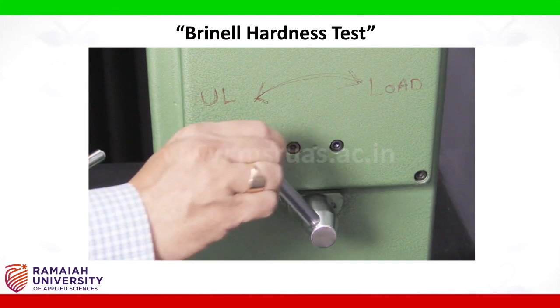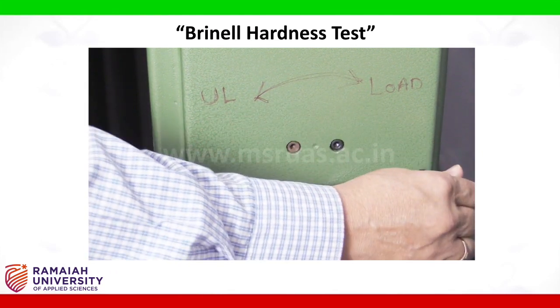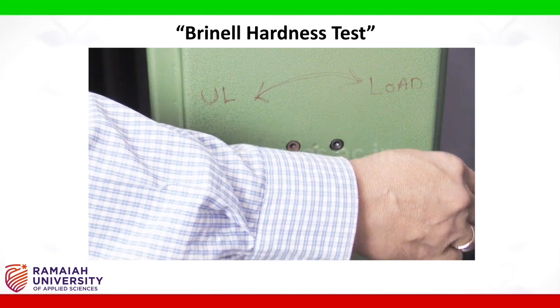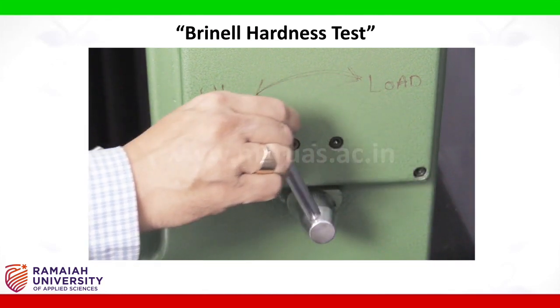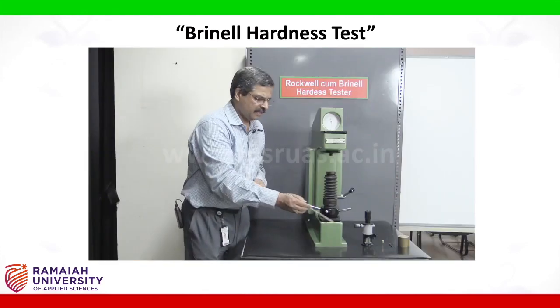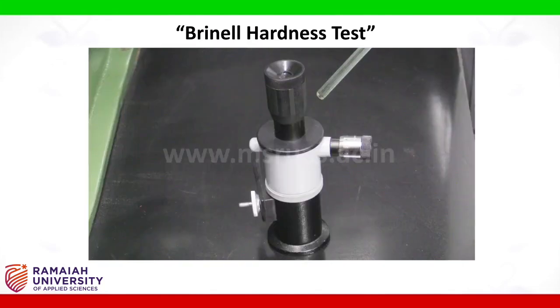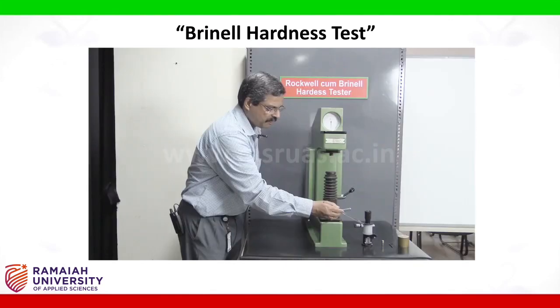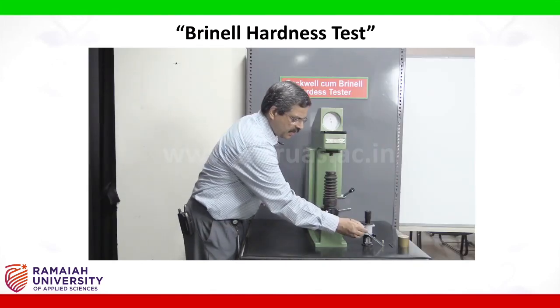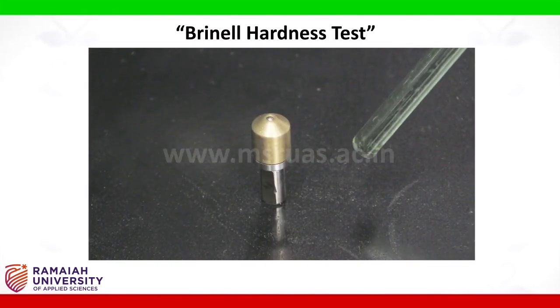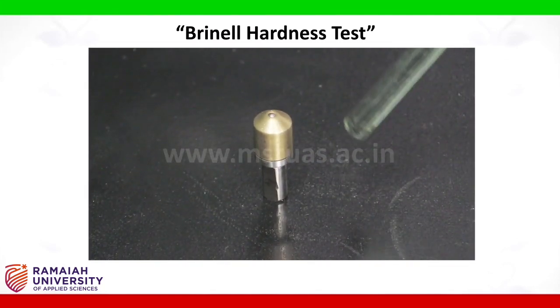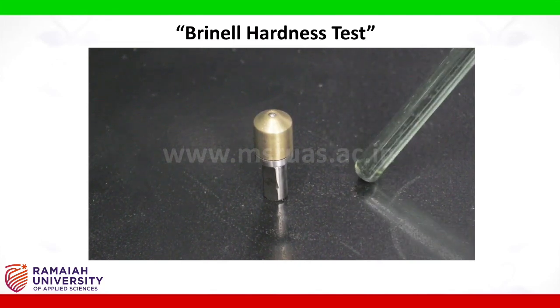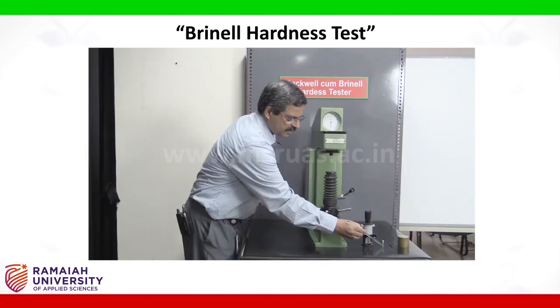When we turn the lever to this side, we apply the load, and when we take it back, we remove the applied load. The Brinell microscope. This is the Brinell microscope, which is used to measure the indentation diameter. The indenter. This is a 2.5 mm ball indenter which we will be using for testing the specimen, brass.